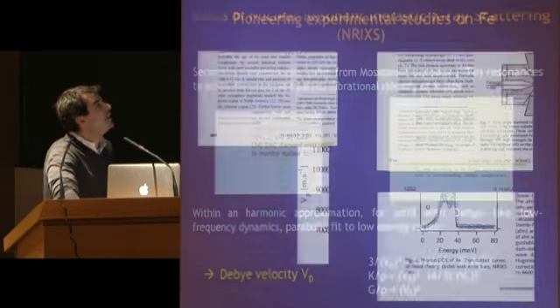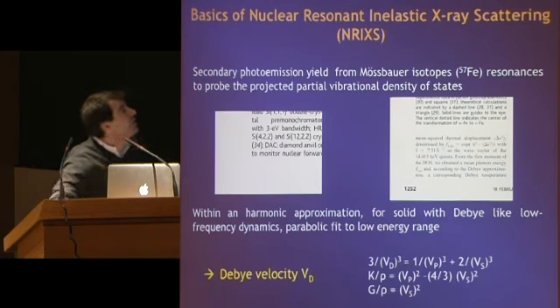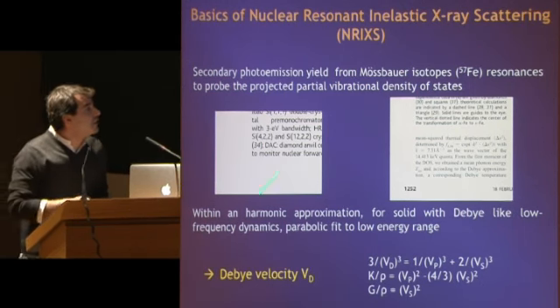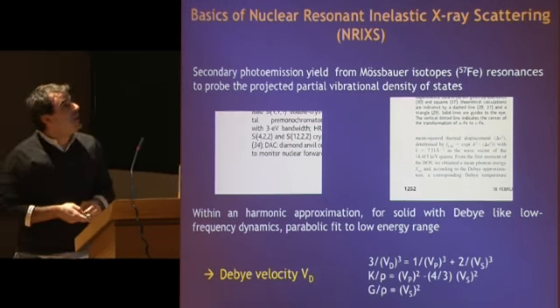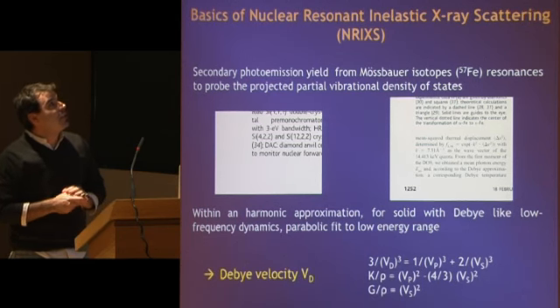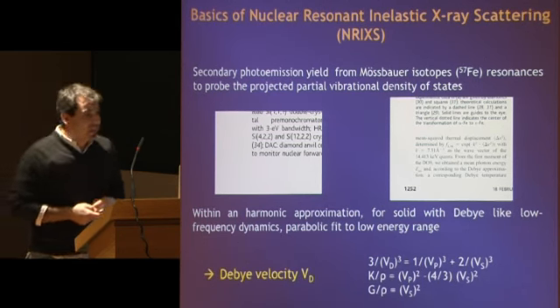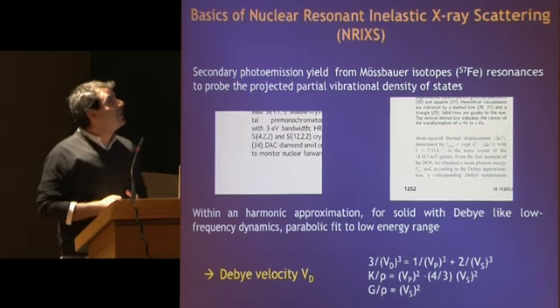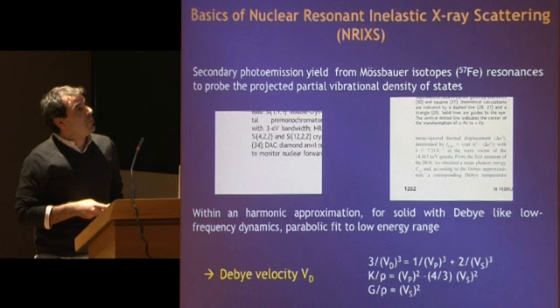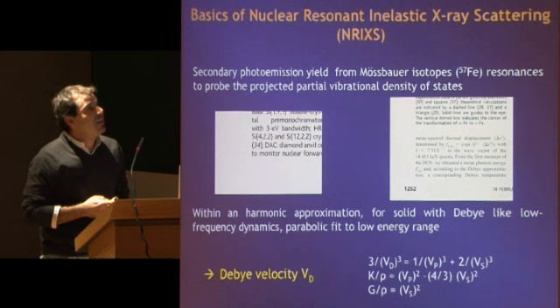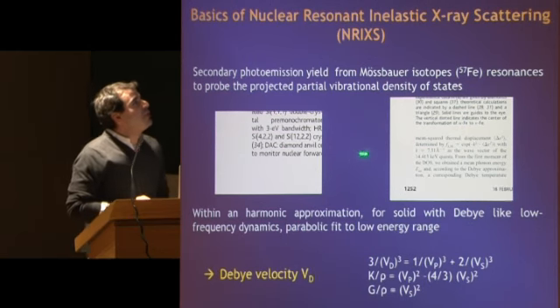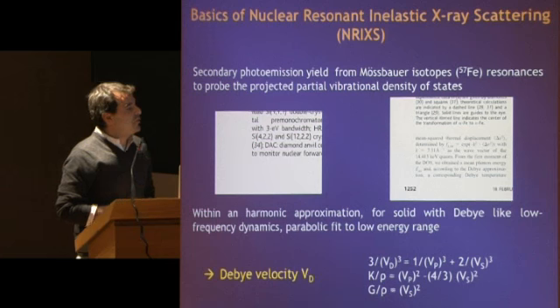But to understand a bit the differences and complementarity of these techniques, I was going to open a parenthesis on these two techniques, and once again, the graphs are not coming. But anyhow, the idea of nuclear resonant inelastic X-ray scattering is that the technique exploits the secondary photoemission from the resonance of Mossbauer isotopes, in the specific case iron-57, to obtain information on the phonon density of states.